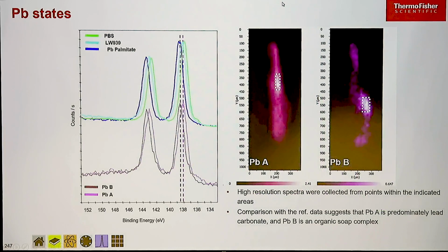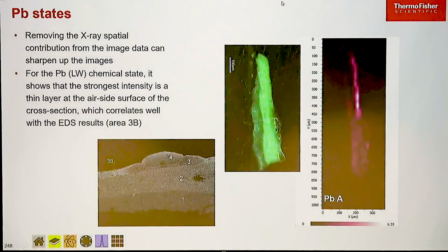So we extracted the spectra from these regions and compared them with the references we'd got. And lead A compared very well with the lead carbonate from Aldrich. So that's this one for the crystallites. Lead B, where we've got that clear blister feature, compares very well with the palmitate, so the lead soap compounds, the organometallic material. And once Jaap, the Dutch scientist that we met way back in Albuquerque, saw this data, he said, "Oh, I know exactly what's happening to this painting now. I know why it's going white and the mechanism that's actually happening."